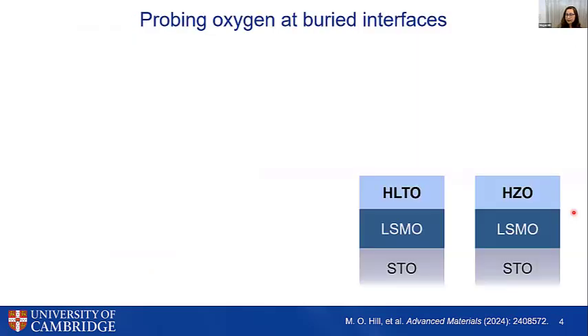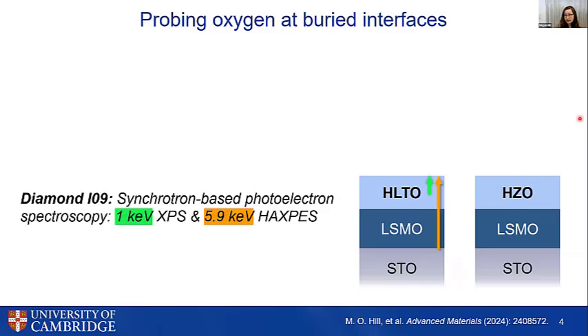And we wanted to investigate these films looking at the oxygen behavior or the electrochemistry overall, not just at the top surface of the films, but at buried interfaces as well, like at the LSMO interface. So to do this, we decided to do a combination of XPS and HAXPES at the I09 beamline at Diamond. Using 1 keV X-rays, we could probe the top about 4 nanometers of our film. And then using 5.9 keV, we could probe deeper into the LSMO.